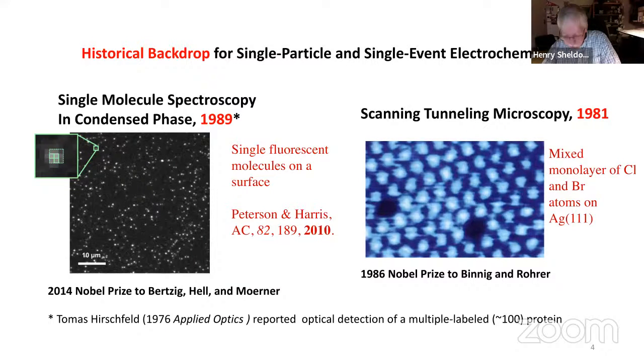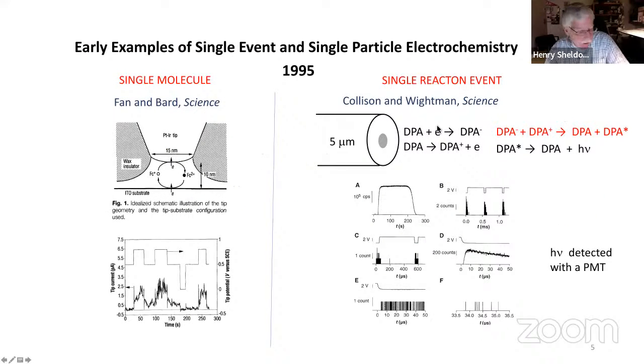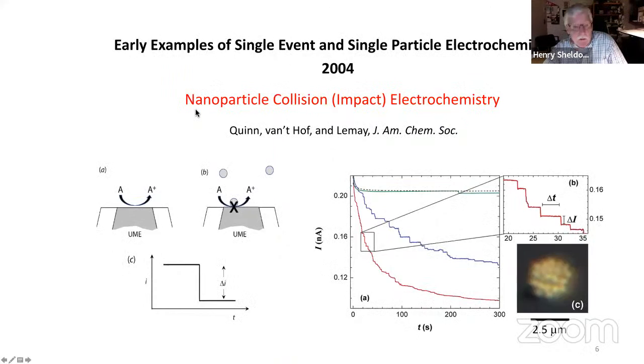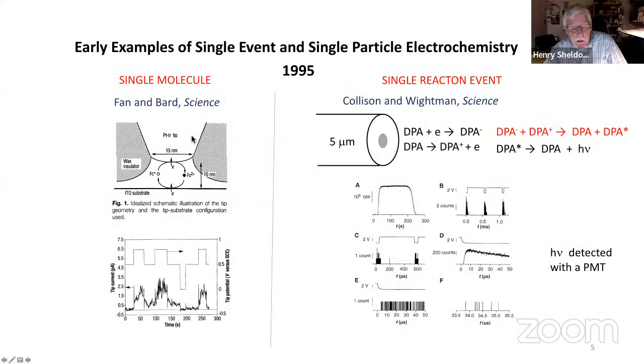So what I want to do now, if I can get my slide to move, is give you a couple of examples of the very first, these are very early on, 1995, first reports of single molecule electrochemistry or single reaction electrochemistry. So the first single molecule paper was from Bard and Fan, published in Science, where they took a scanning electrochemical microscopy tip, a metal tip, very sharp tip, with a diameter of about 15 nanometers, and brought it up to a surface within 10 nanometers and trapped a single molecule of ferrocene. I'm sorry, my slides are jumping. And then you can oxidize the molecule at the tip, and then it diffuses to the substrate where it's reduced, and you cycle this over and over 1 million or 10 million times per second, and you generate enough charge to actually measure the electrochemical current.